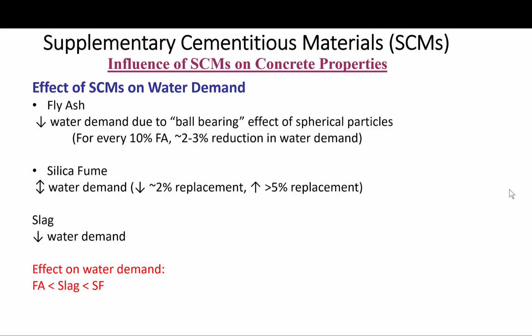Silica fume may increase or decrease the water demand depending on the replacement level. For 2% replacement, water demand is reduced. For more than 5% replacement, water demand is increased. This is due to the very fine and sticky nature of silica fume, which makes handling difficult. Slag reduces water demand. So if you compare these three products, fly ash, slag, and silica fume, the most reduction in water demand comes from fly ash, followed by slag, and then silica fume.